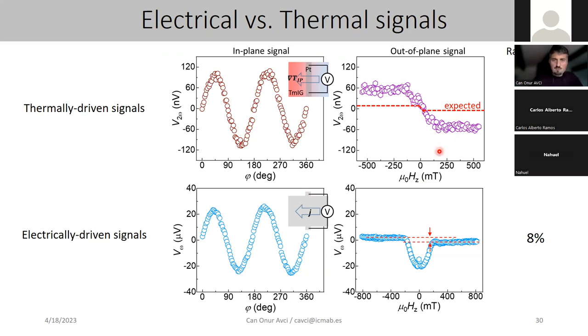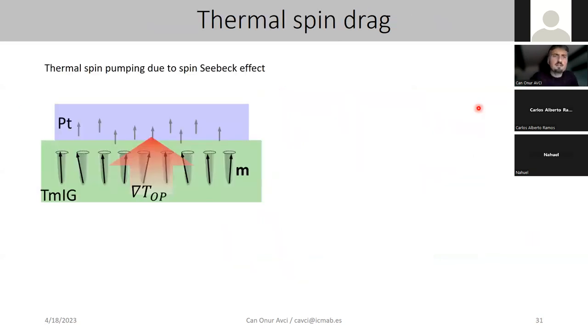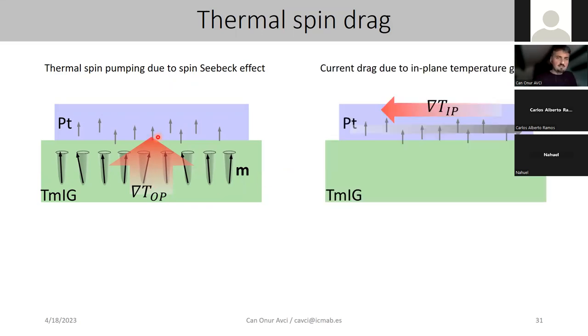If there was a one-to-one correspondence, the expected signal would have been this red one. But we had a signal somewhat 10 times larger than what we expected. Our explanation is that this could be due to the combined action of out-of-plane gradients pumping a spin current into the platinum with an out-of-plane polarization. Then you get an in-plane temperature gradient that also drags this spin current along a certain direction.